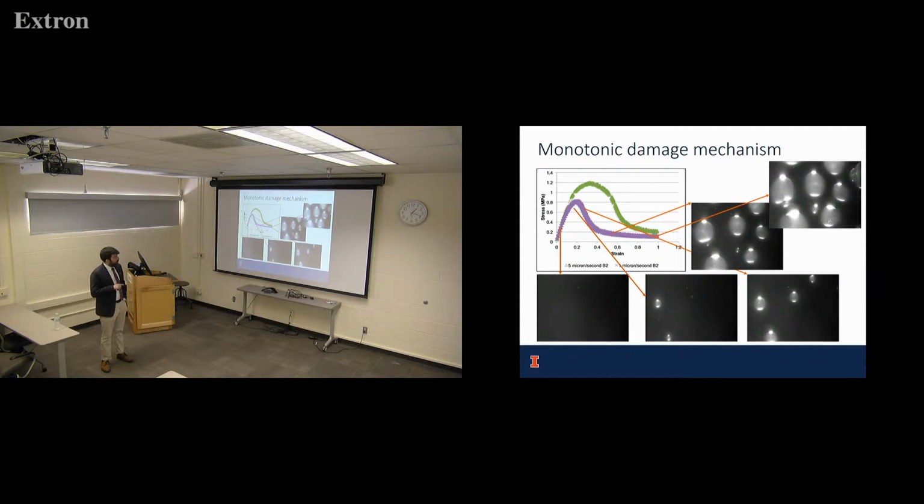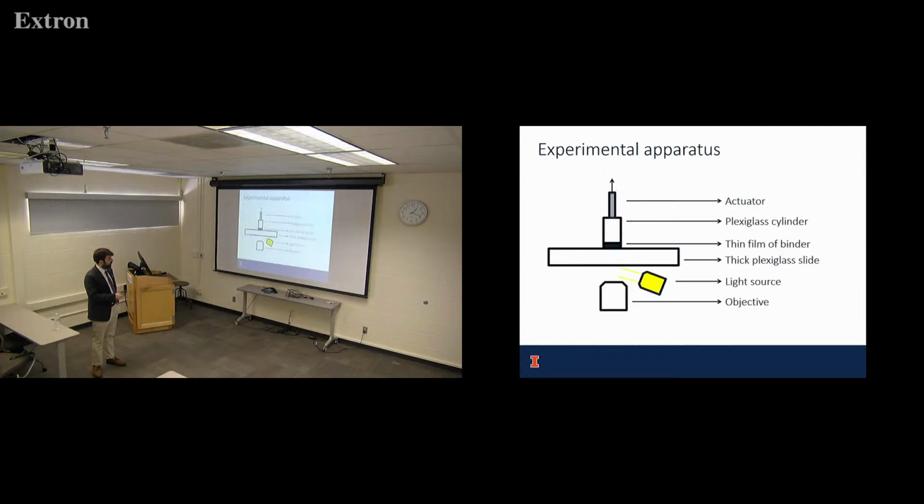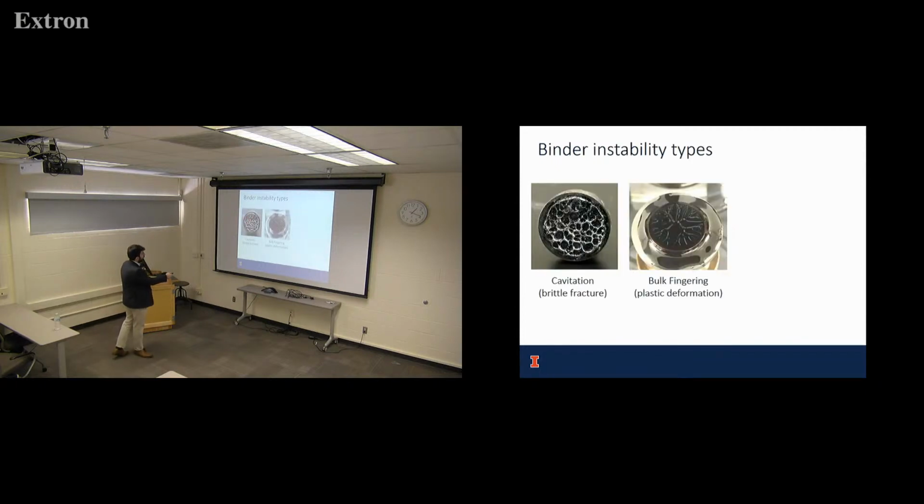So what we did is we used the exact same aspect ratio and loading conditions as a poker chip test. Yeah. And in the poker chip test, with those exact same conditions, the only difference being it wasn't done on the microscope, we did verify that because we looked here, like these images. Oh, it looked like the one on the right. Exactly, on the left. On the left? So yeah, the one on the left. So actually, you do see this. There, we put a white powder so you can see the difference, but you can see on the back that there is binder underneath.